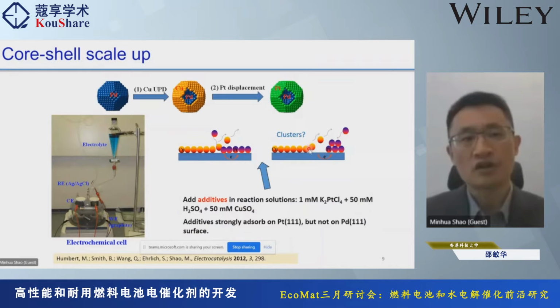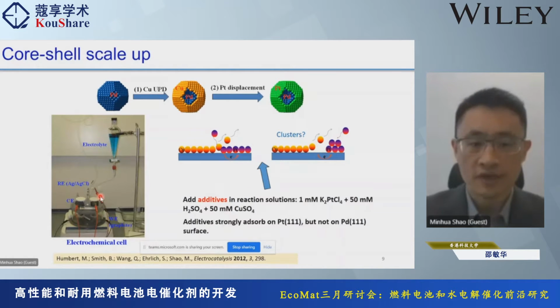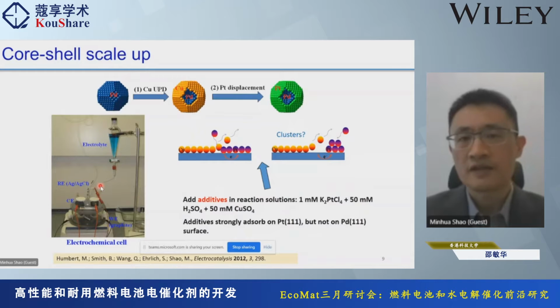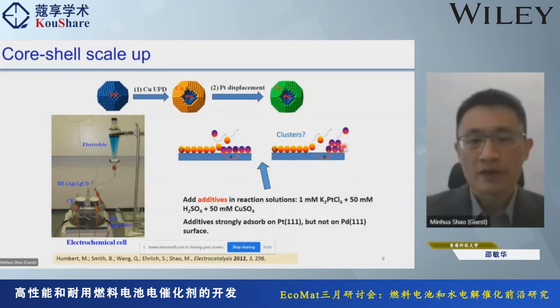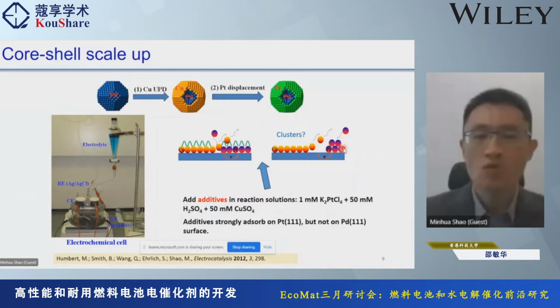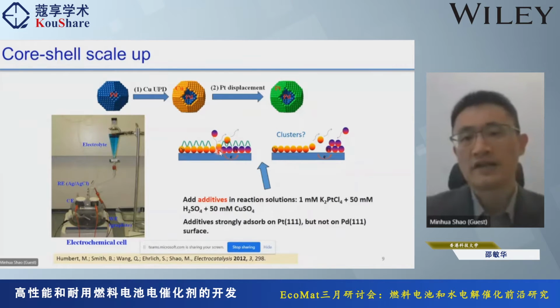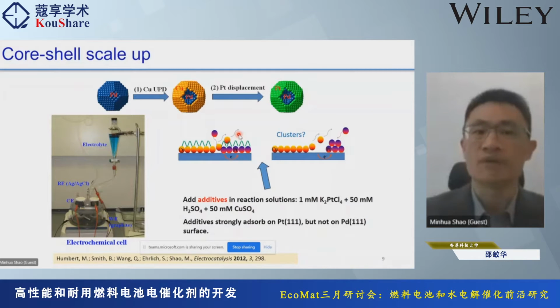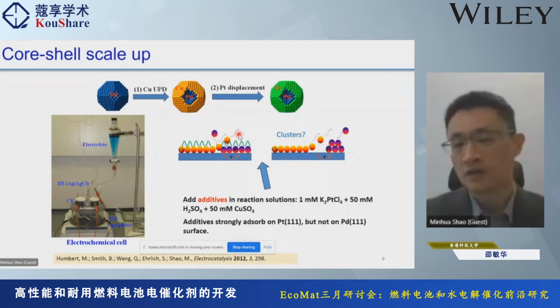If we want to produce a lot of the core-shell, basically you need to design a reactor so that it can give you at least a gram of material to be tested in the fuel cell. And we found that it's not easy. When you scale up, instead of forming a platinum monolayer, most of the time you form platinum clusters. So can we have a physical block to prevent further deposition of platinum? Basically, if we have something that adsorbs on the platinum or copper surface, then the only place the platinum can go is the site that the copper atom left. So you can use this as a template to guide the deposition of the platinum atoms.